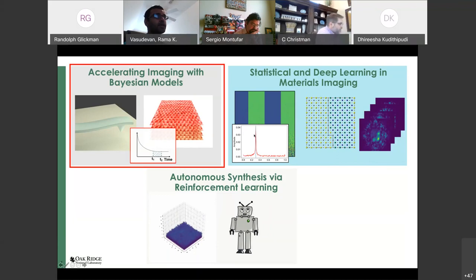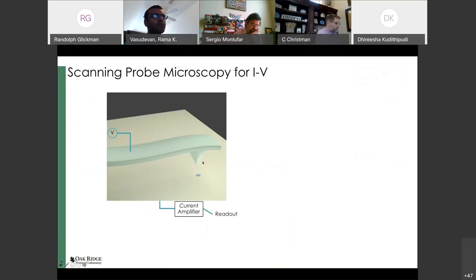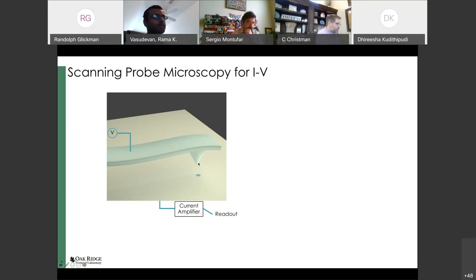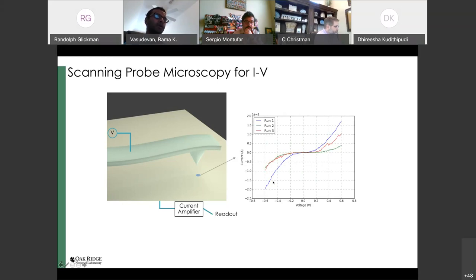I'm a microscopist by training, and we deal with scanning probe microscopy, which means we have a tip at the end of a cantilever. We apply some kind of stimulus to the tip and measure a functional response of the material at a particular position. With an electrically conducting tip — either STM or AFM — we can apply a potential and measure the current that flows as a function of voltage. At any one position, sweeping the voltage produces IV curves. This technique has been used for 25 to 30 years to map electrical properties at the nanoscale.